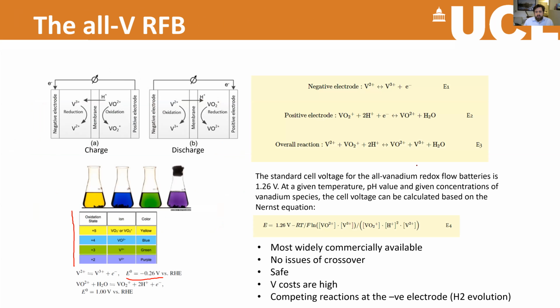One of the key benefits of the vanadium flow battery is that you can do that electrochemically. So if lots of vanadium-2, for example, has passed over into the positive electrode, you can take that positive electrolyte and regenerate it by changing it back to vanadium-2, putting it back into the system and starting with a fully charged electrolyte. This also actually has some benefits. The fact that you can change these electrolytes very easily just by emptying your tank and filling it up with something else means that you can very quickly recharge these systems. So you could take the spent electrolyte out, put some new electrolyte in, your system is ready to go and is back online very quickly.